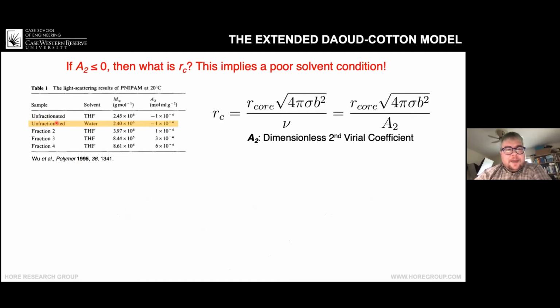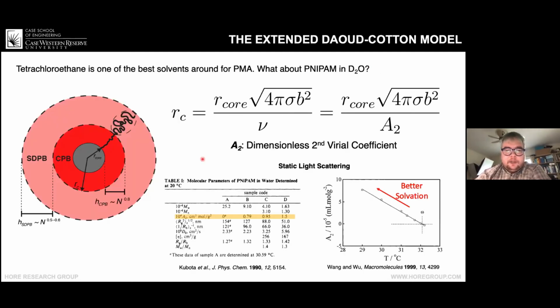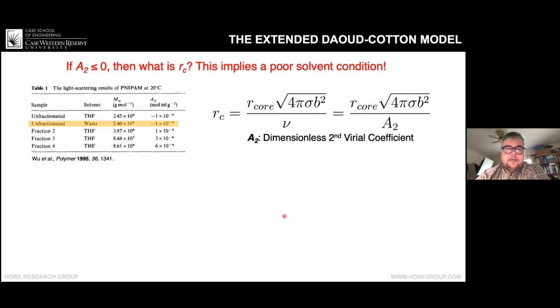This is poly-NIPAM at 20 degrees C in water with a molecular weight that's actually similar. It's actually between the two values here in the previous study. Second virial coefficient is negative, which implies that the solvation is not so great. Well, if you look at the Daoud-Cotton model, if this goes negative, then what does that mean for RC? It becomes negative, which is kind of nonsensical.